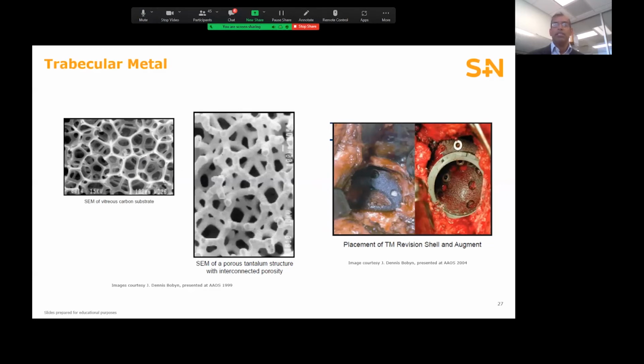One material that's been used in such cases is trabecular metal. This material is built by depositing elemental tantalum onto a carbon substrate using chemical vapor deposition. The resulting structure has interconnected porosity and is reported to have modulus similar to cancellous bone, which has benefits from a stress shielding perspective. It can be fabricated both in the form of a shell or an augment, which you can see in the images on the right. When this was launched, it was quite successful as porous structures were a bit limited.